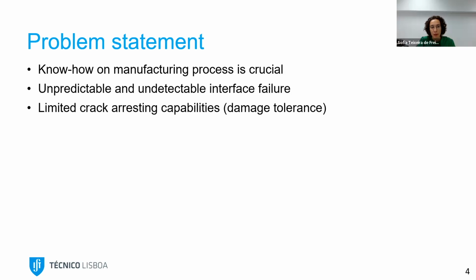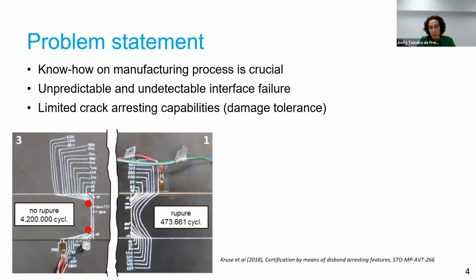Another challenge is the limited crack arresting capability of a bonded joint. What does this mean? It means that once you have a crack on the bond line, the crack can propagate very suddenly and cause a catastrophic failure of the joint, because there's nothing that stops the crack from growing. And I would like to give you an example of it.